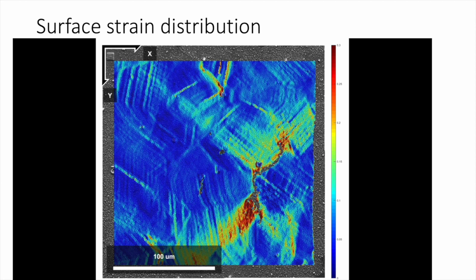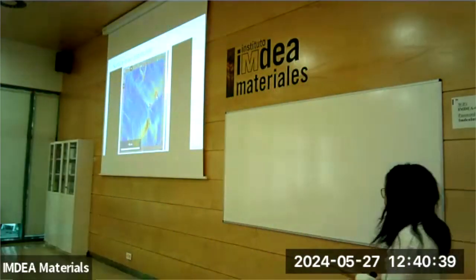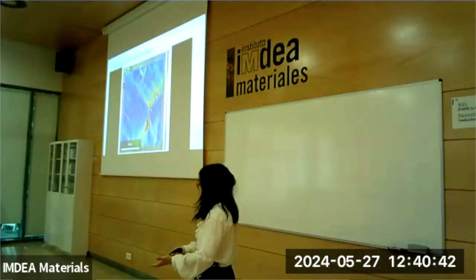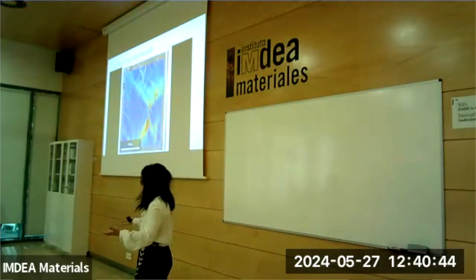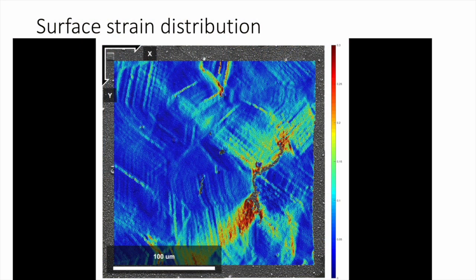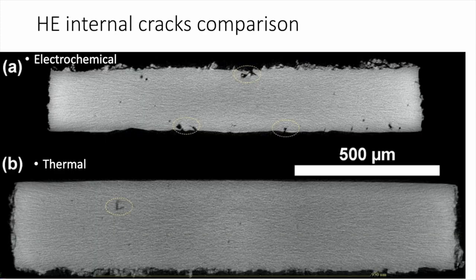As you can see here, we did not get as many slip bands compared to what we had in our electrochemically charged sample. We're wondering, so what makes it so different? Why in one case do we have a lot of surface cracks, and in another case we just have one crack and fewer slips? So maybe there's something inside. So we took both of the samples and did a CT scan to see if there's any difference in terms of the internal cracks. This is just one slice we took from the cross-section of the material.